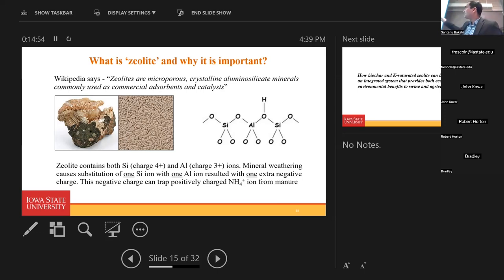Basically, zeolite contains both silica and aluminum ions, which are 4+ and 3+. Now, mineral weathering causes substitution of one silica ion with one aluminum ion, resulting in one extra negative charge. This negative charge can trap positively charged ammonium nitrogen from the manure. So you can engineer the surface of the zeolite with ammonium, or you can engineer it with H+ to be used as an acid catalyst. Zeolite has a very high cation exchange capacity. So that's why zeolite is very important here if you want to trap the ammonium.